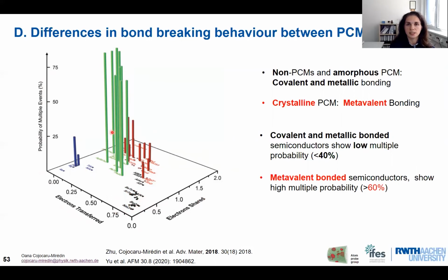And we see nicely that for these compounds, we have a very high probability of multiple events, which is much higher than 60%. Which means that the bond breaking mechanism is not a stochastic behavior. So it's really correlated with the electron behavior down to the bonding level.